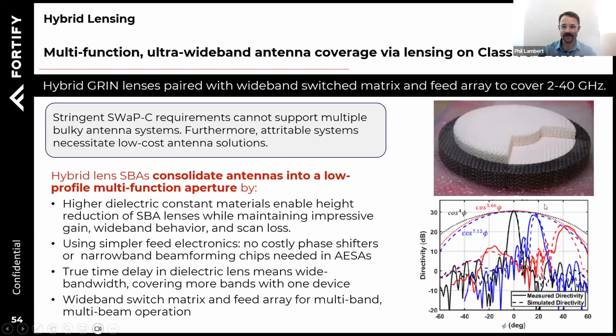And so this is what the result of that design was: multifunction ultra wideband antenna coverage via lensing for Class 1 or Class 2 UAVs. That's the application for this lens. It's a hybrid lens for a switched beam architecture, very similar to the one I was describing before, that covers 2 to 40 gigahertz, so super wideband, and it takes advantage of combining those dielectric materials together to create a high gain, fairly low scan loss, low profile antenna lens system.